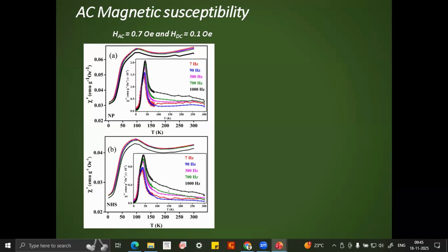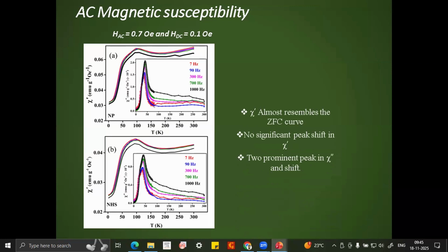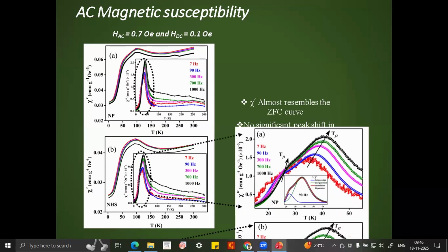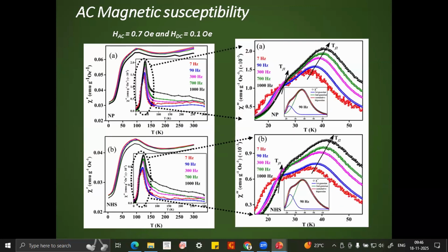Now, you can see that the real part is also not very different for the two systems. On the other hand, if we zoom into the imaginary part, that is chi double prime, then something interesting happens. We can see that we are actually getting 2 peaks. The 2 spin freezing temperatures are there, one around 25 Kelvin, and another around 35 Kelvin.